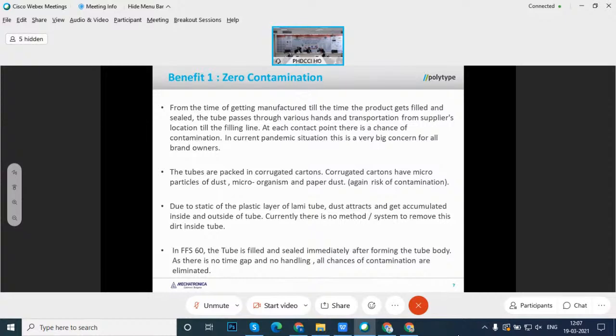But you cannot do it from inside the tube. Okay, you may, but it's extremely difficult. So usually, even if you do it from outside, you have static charges inside the tube, and when you put it in the box, whatever dust is there during this sonic rotation may go inside the tube and stick to the inner surface and stay there. And then during filling, removing this dust is not easy at all.